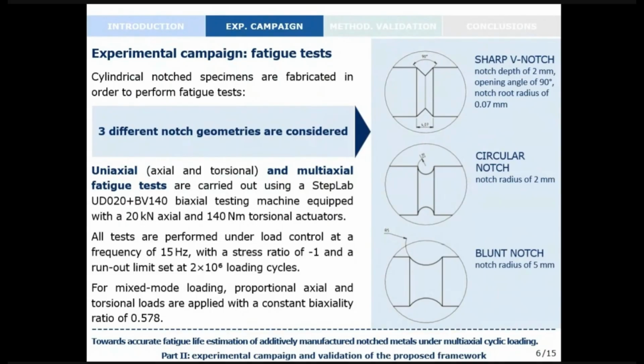3 different notch geometries are considered, as you can see on the right of the slide. So we have a sharp V notch with a notch depth of 2 millimeters, an opening angle of 90 degrees, and a notch root radius of 0.07 millimeters. Then we consider a circular notch with a notch radius of 2 millimeters, I will call it C2 notch later, and a blunt notch with a notch radius of 5 millimeters that I will call C5 notch.